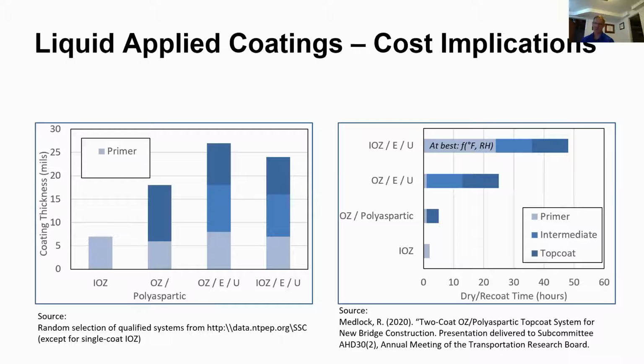So when a fabricator is fabricating a plate girder, for example, after it's done being fabricated, it goes into their paint bay. And if you have to apply three different coatings, then it's going to take a little more time for the coating system to dry that was previously applied, and then to apply the next one. But the main thing I want to point out here, and I think you can see my cursor, is up here. When you use an IOZ coating in a 3-coat system, it's very dependent on the relative humidity and the temperature for that IOZ to cure. Now down here, this is also IOZ, but this is just one coat. The fabricator can simply take this bridge after it's coated, move it out of the way, and it doesn't affect their throughput, and therefore doesn't cost as much.